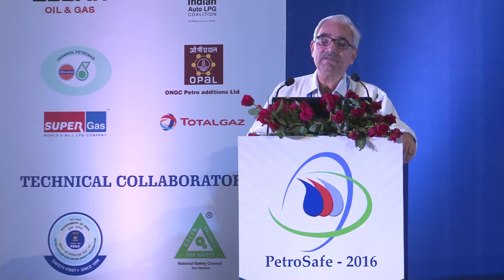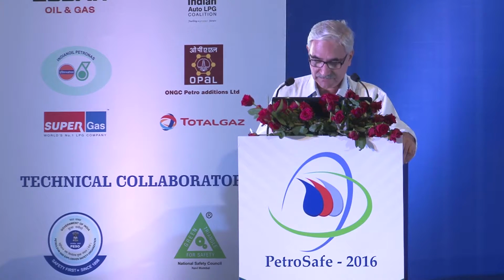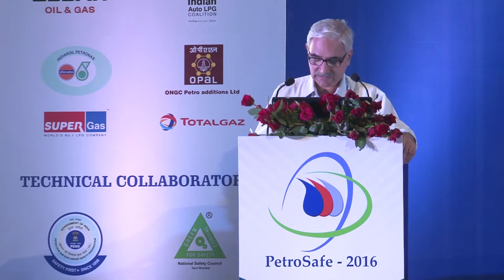So what we have done in this case is, we have provided an internal coating on the bottom side. By providing internal coating, we are avoiding, in case any wet H2S is coming and any liquid is coming, that it will not be directly in contact with the steel. And second thing is, the hardness has to be monitored periodically in every M&I, and we have to ensure that it should be around 200 BHN.